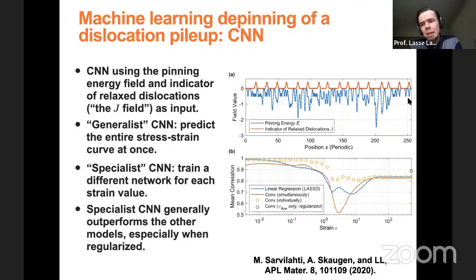So then you can do two different types of CNN here. What you call generalist and specialist CNN. So the generalist CNN tries to predict the entire stress strain curve at once, while the specialist is trained to learn a specific stress value corresponding to a specific strain. So it's like a special task rather than a general task of predicting the whole thing. And it seems that the specialist CNN usually is able to do better than the generalist one.